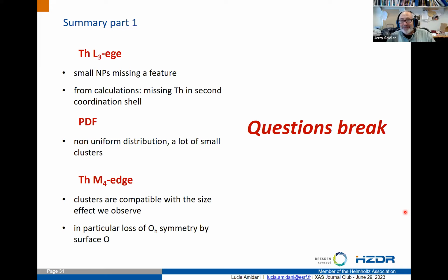One last question. ESRF after the upgrade has spectacular brilliance. And one of the main things affecting your analysis is that you may have a distribution of different nanoparticle moieties. Do you have enough brilliance, enough flux to disperse the nanoparticles, microfocus or nanofocus your beam, and look at the fluctuation in the XANES, nanoparticle to nanoparticle variation, and actually sample the distribution rather than modeling it?